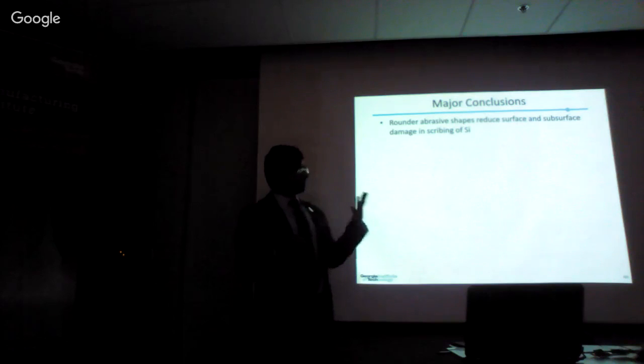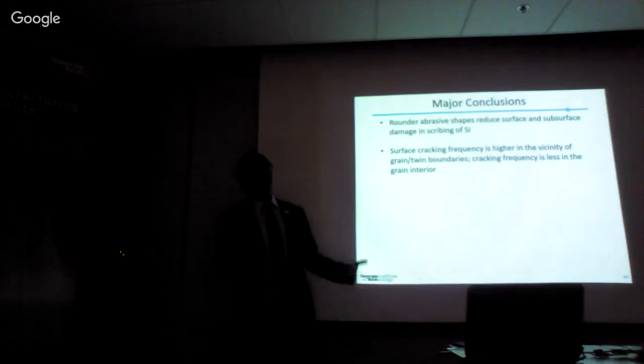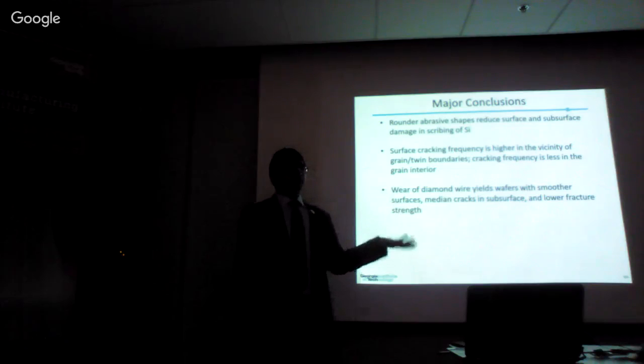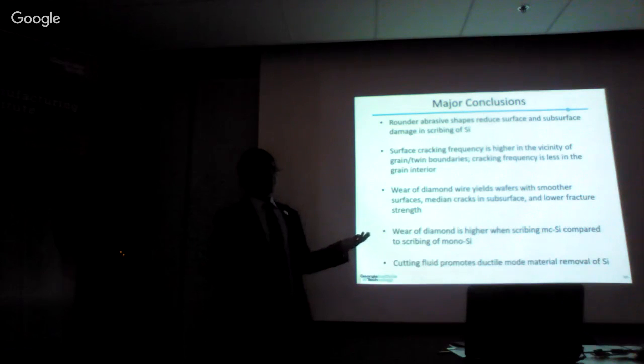So to revisit the major conclusions from the different tasks, we found that rounded abrasive shapes reduce the surface and subsurface damage in scribing of silicon. We found that the surface cracking changed across the boundary of grain and twin boundaries in the vicinity, but becomes similar away from the boundary. We found the wear of diamond yielded smoother wafers, but median cracks in subsurface and reduced the fracture strength of wafers. We found that the wear of diamond is higher when scribing multi-crystalline silicon compared to scribing monocrystalline silicon. And finally, that cutting fluid chemistry would promote the ductile mode material removal of silicon.